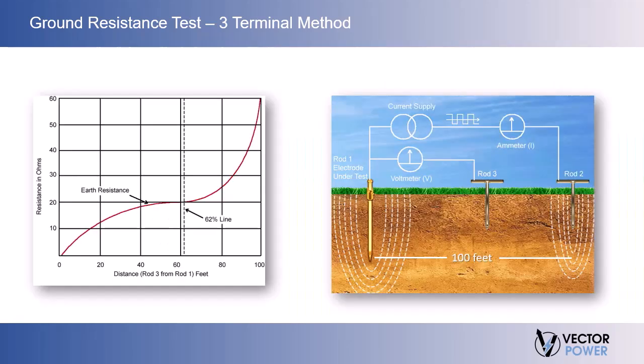A series of resistance values can be plotted against distance to obtain a curve. Note that as rod 3 is moved away from rod 1, the resistance value increases, but the increase gets less and less until the point is reached where the rate of increase becomes so small that it can almost be considered constant. 20 ohms for the example shown. The earth shell between rods 1 and 3 have such a great surface area that they add little to the total resistance. Beyond this point, as rod 3 approaches the earth shell of rod 2, resistance gradually picks up. Near rod 2, the values rise sharply.